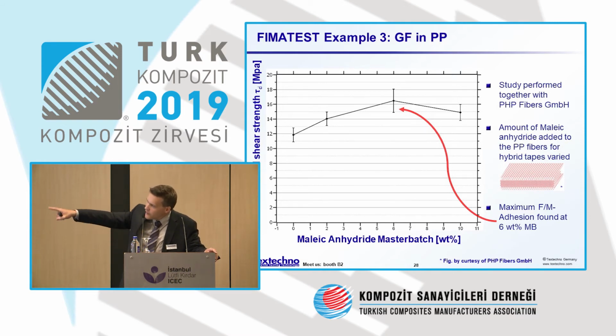And you see the local interfacial shear strength as a function of maleic anhydride in the spinning processes, which is added through a master batch. And you see that it's peaking at around 6%. So we help them to optimize their spinning process in terms of adhesional properties for their final composite.